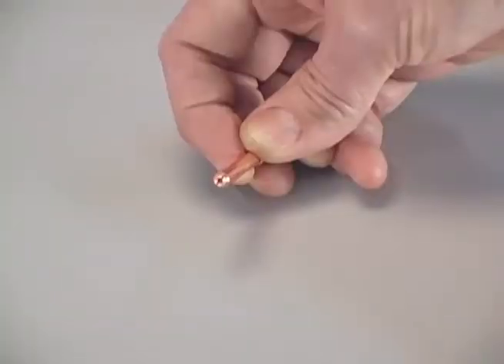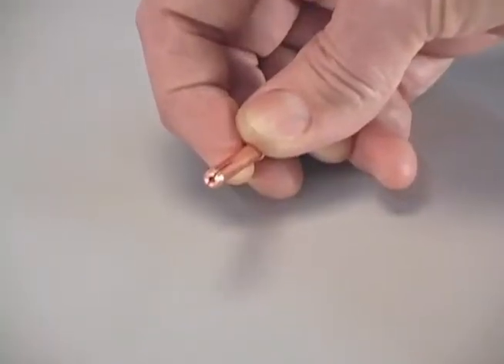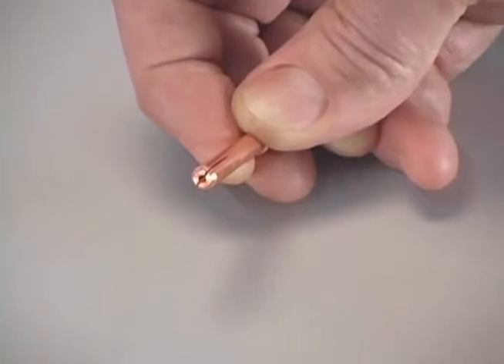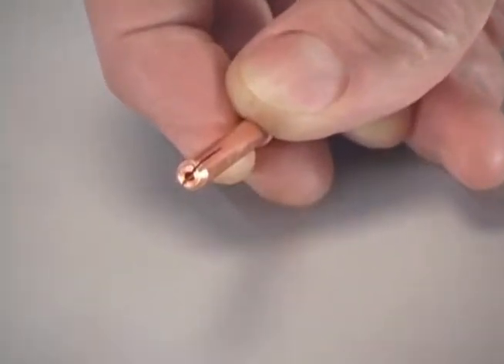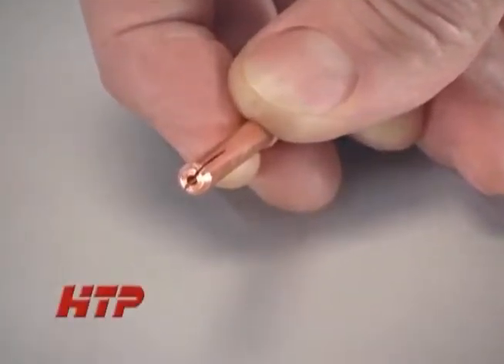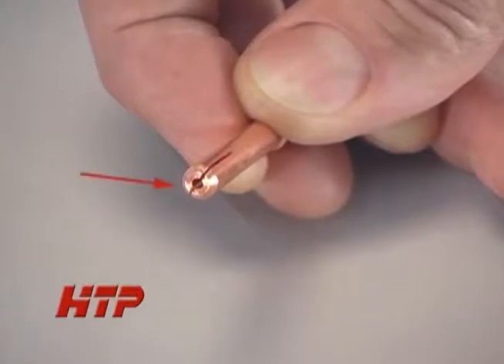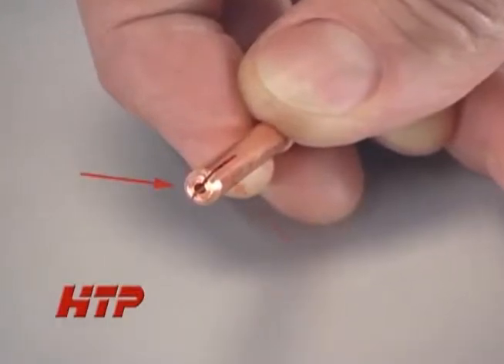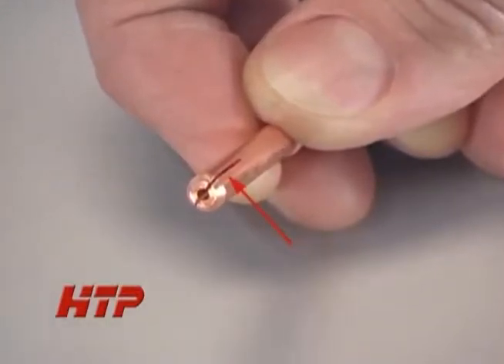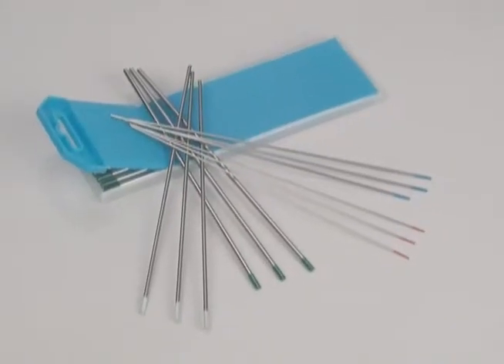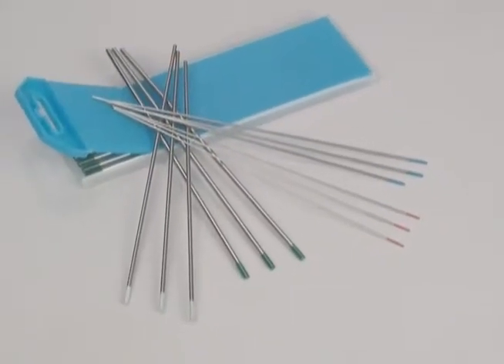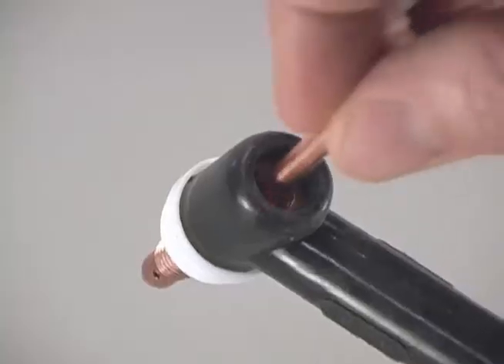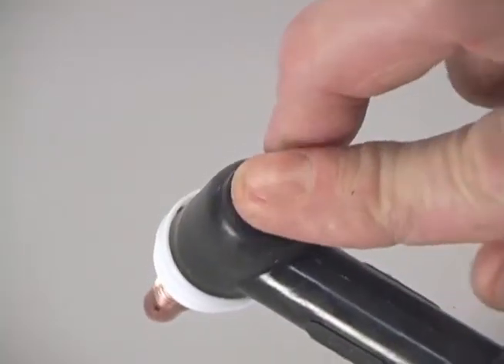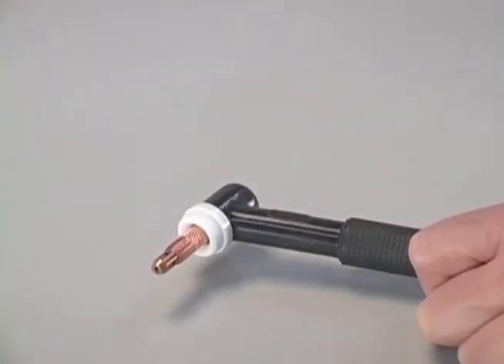The collet is a 1 to 2 inch long piece of copper. It takes the welding current from the torch head and transfers it into the tungsten. Like the collet body, the collet is also matched to the diameter of the tungsten. You can see a slit in the collet, which allows the collet to grab the tungsten when the back cap is tightened. Place the collet in the torch so the slits will bottom against the collet body.